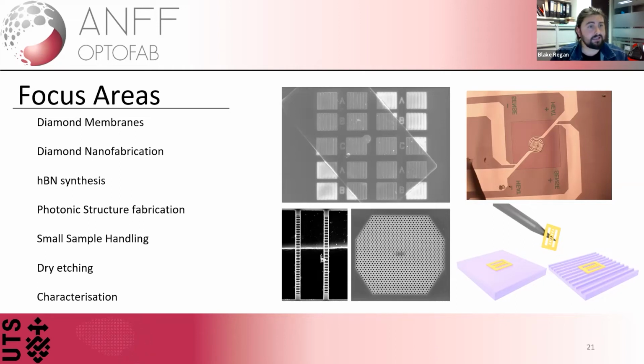In discussion of small sample handling, I've done a few projects, one specific with UNSW, where I was simply capable of holding those. They had needed diamond membranes being handled and cleaned, which I was more than happy to do. Most people work with diamond plates, which are the scale of almost 0.5 millimeter, whereas I'm used to working with samples by hand that are about 50 micron.